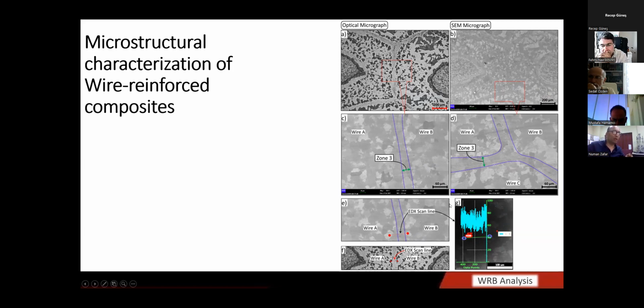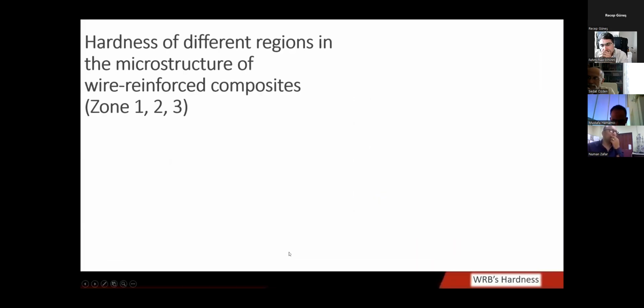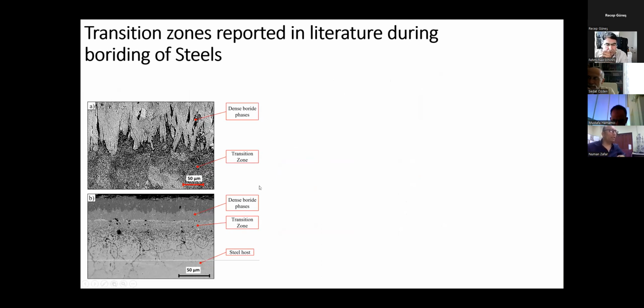So we needed to see what is going on. We did an EDX analysis running from one wire to another wire, and we saw that the carbon content at the interwire boundaries was lower compared to the regions belonging to the different wires. So we can safely say that these regions are indeed carbon deficient regions. Why have they formed? That might be because of the diffusion of carbon from the sheath to the cores at the region of intercore wires.